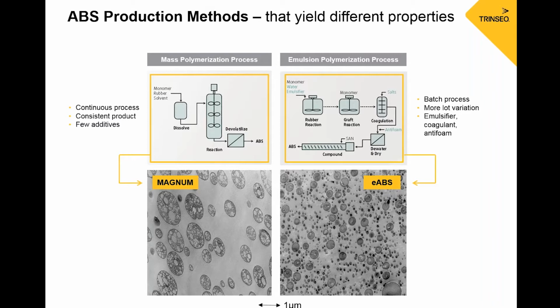Another aspect of the benefits with mass ABS is the rubber particle sizing, which you can see in the bottom two images resulting from these two processes. With the mass ABS on the left, you can see much larger rubber particle size versus the emulsion on the right. This image is taken using transmission electron microscopy, and the light gray is the continuous SAN phase, and the darker color that you see is the rubber itself. How we get that image is we stain the rubber with a solution, and that solution shows where the carbon-carbon double bonds are in the rubber itself, and so that's how we see that. And remember that will become important on a slide later on.